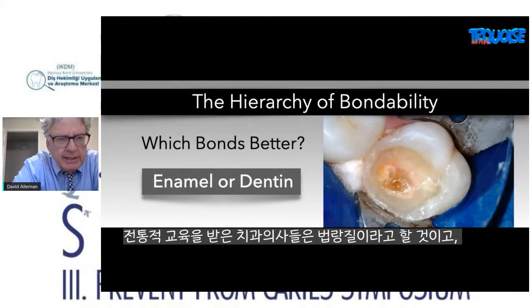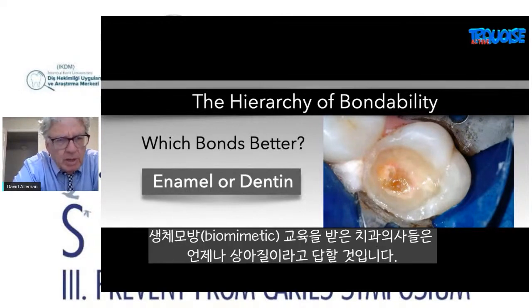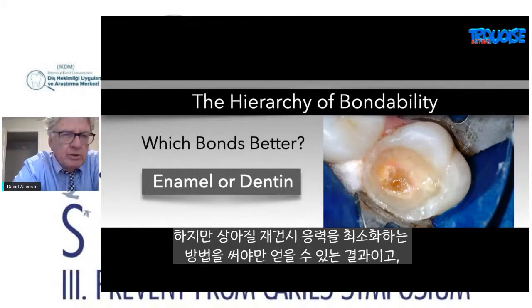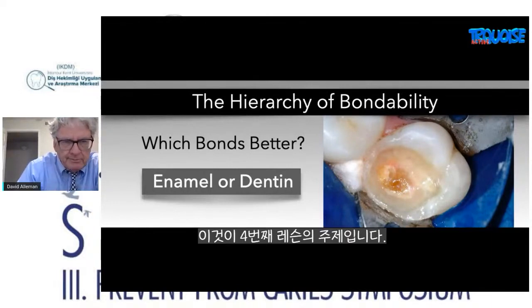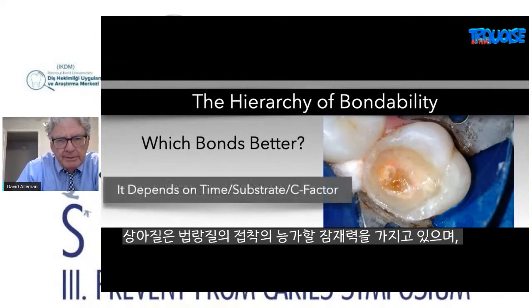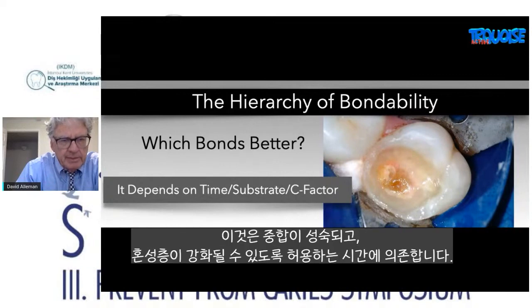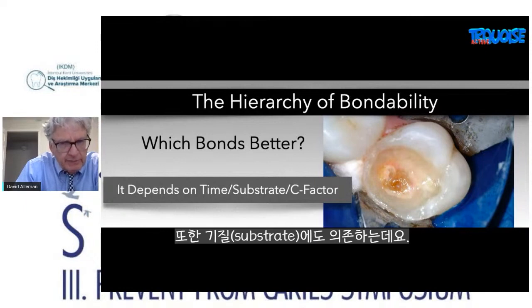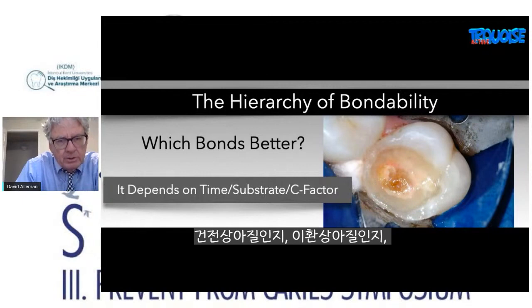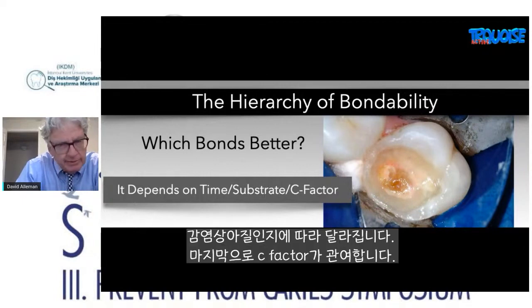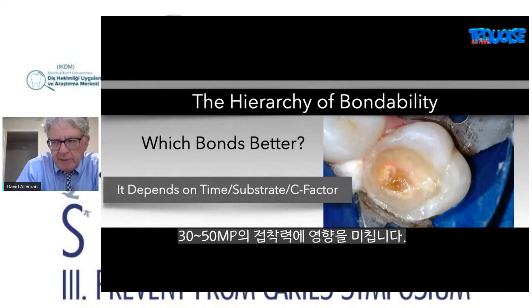Traditionally trained dentists will say enamel. Biomimetically trained dentists will always say dentin, but that's depending on using a stress-reducing technique for the dentin replacement, which is our lesson 4 topic. And so dentin has the potential to bond better than the bond to enamel, but it depends on the time that the polymerization is allowed to develop and strengthen the hybrid layer. It also depends on the substrate, if you're bonding to carious dentin or over cracks or over sound dentin or caries affected dentin or caries infected dentin, and it also depends on the C factor. So all of these considerations affect the bond strength that we're shooting for, which is in the 30 to 50 megapascal range.